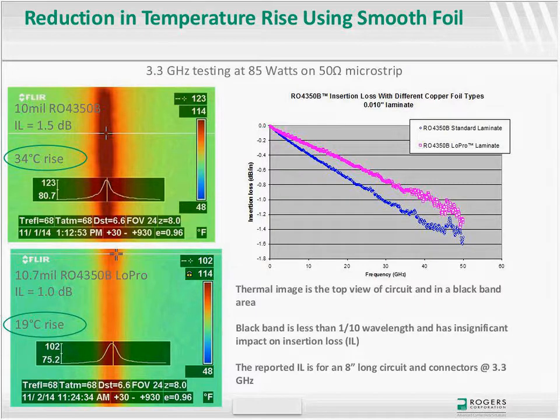But the important factor here is looking at the impact that smooth copper has versus rougher copper. Traditionally, many of these materials come with options of rolled copper or electrodeposited copper. In general, rolled copper has a smoother surface at the interface between the copper and the dielectric. Smoother means lower conductor losses, so that's an advantage. The higher the frequency or the thinner the dielectric, the more of a factor this is.